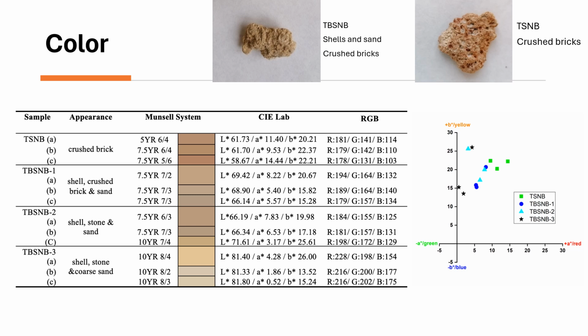Meanwhile, the graph shows the CIELAB coordinates obtained in all the points analyzed in the wall. Despite the dispersion in the results, the higher value of the A coordinate of TSNB as compared to the other areas is clearly highlighted, coherent with the reddish tone of this area. TBSNB-1 and TBSNB-2 show similar values of the three color coordinates, and TBSNB-3 shows the lowest A and B values and the highest L values, which correspond to the lighter yellowish appearance of this area. The results obtained by the colorimeter are consistent with those determined by the Munsell system.